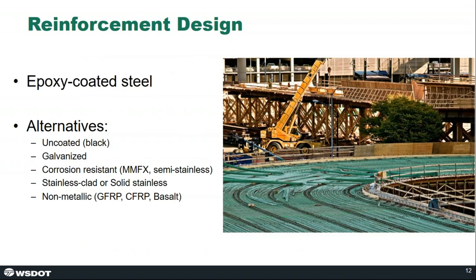A note about the reinforcement that we use. In our bridge decks, we use exclusively epoxy-coated steel. This is quite common throughout the country. In the past, we limited epoxy-coated steel to the top mat of reinforcement and had specified uncoated steel on the bottom mat. But with the amount of cracking that we had been experiencing, there was concern that the bottom mat was also not adequately protected. So we're currently specifying epoxy-coated steel throughout our bridge decks.